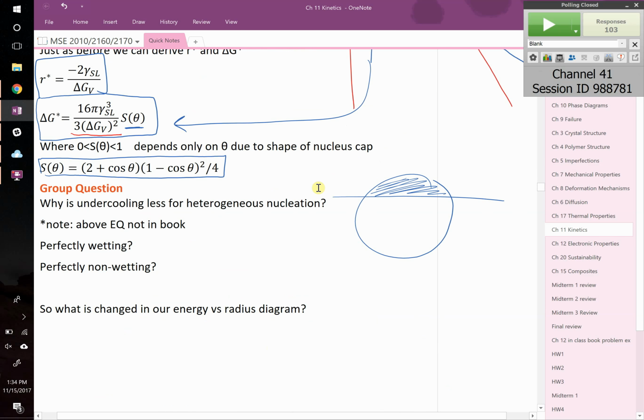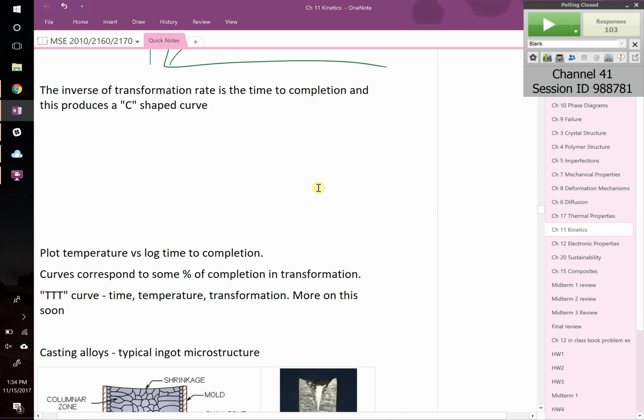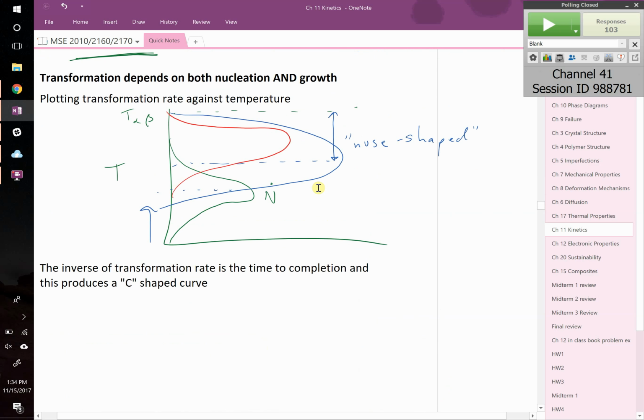Yeah, question, Elise? Would you be able to do the same thing with martensite? Yeah, we'll talk about martensite in just a minute. Martensite, that's a perfect example of basically quenching it so fast that you never are in the region of this nose where it is going to transform. So you quench a high temperature phase down to room temperature. But would you be able to give it some activation energy? We're going to talk about that. You absolutely can. Yeah, you can go from martensite back into some of these other steels. They call it tempered martensite. And it's one of the better grades of steel out there because it has a mix of both properties. It has good hardness, but it has some significant ductility.